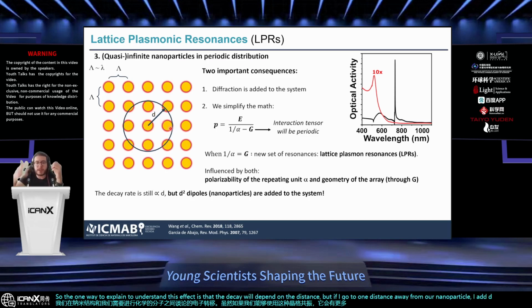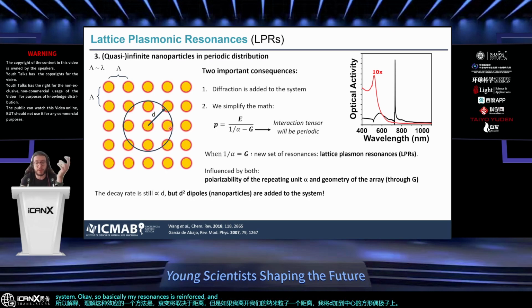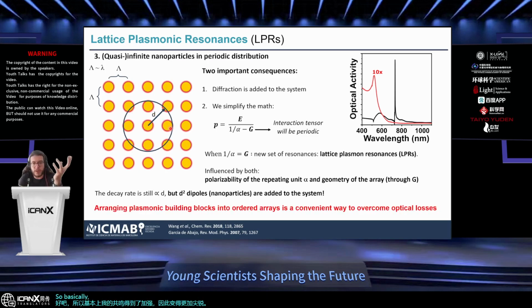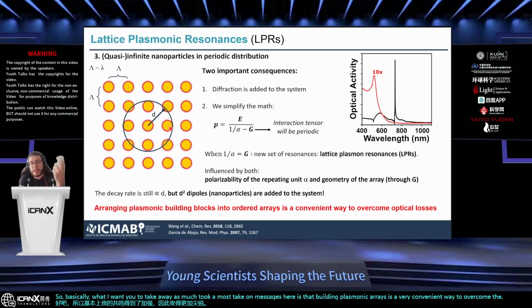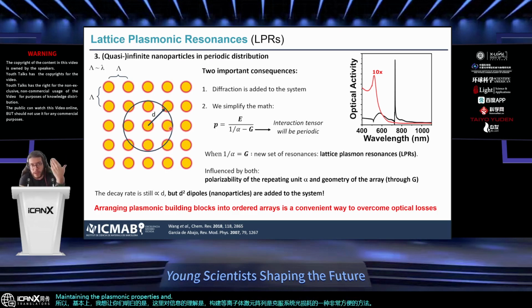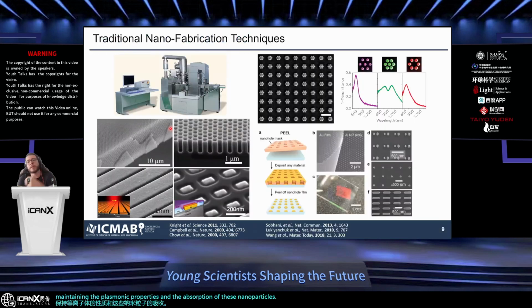Okay, so basically my resonance is reinforced, and therefore it becomes much sharper. So what I want you to take away as take-home messages here is that building plasmonic arrays is a very convenient way to overcome the optical losses of the system, maintaining the plasmonic properties and the absorption of these nanoparticles. Traditionally, these types of metamaterials and plasmonic metasurfaces have been fabricated using what we can call traditional nanofabrication techniques involving complex evaporation and electron beam lithography, which have proven to be extremely helpful in understanding this type of system and also in applying them in several fields.